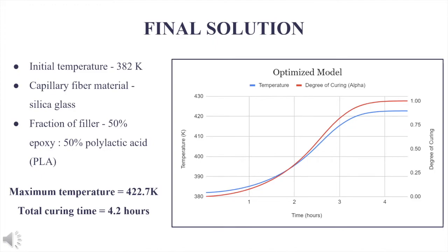For our final model, we chose to keep the capillary fiber material as silica glass because it's the safest and most economical material to use. The ideal ratio of filler material is 50% PLA to 50% epoxy. Under these conditions, the ideal initial temperature for the reactor is 382 Kelvin, which leads to a total curing time of approximately 4.2 hours and does not cause the reactor to exceed 425 Kelvin.